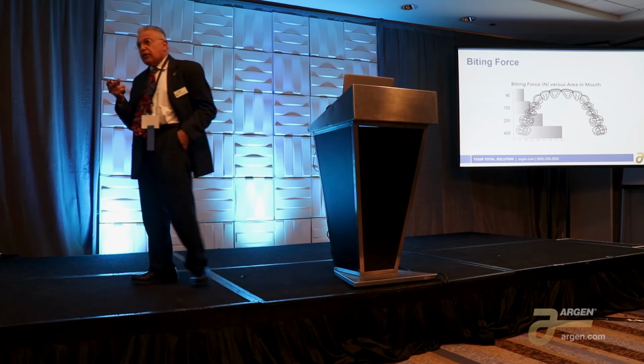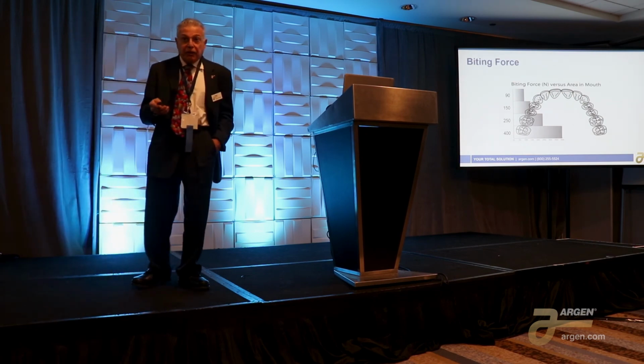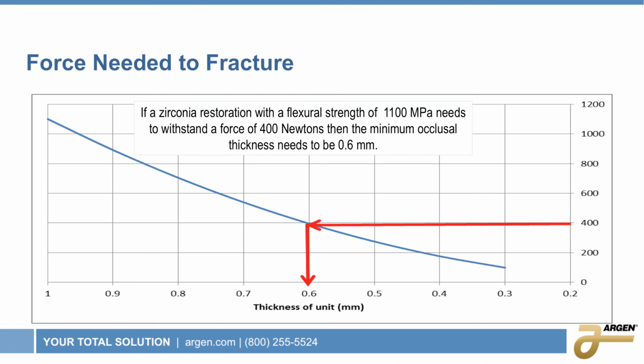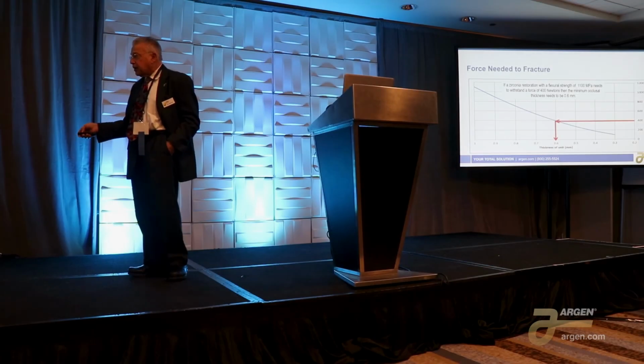Okay, so 400 newtons. If we know that our material has to tolerate a biting force of 400 newtons, and we know the strength of the material, so here we have a zirconia restoration with a flexural strength of 1,100 megapascals, and it needs to withstand a force of 400 newtons, then we could calculate what the minimum occlusal thickness needs to be, and that's 0.6 of a millimeter.